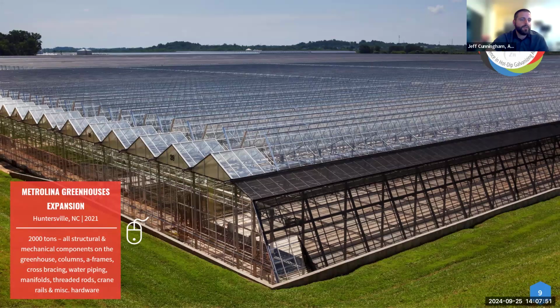So this is the Metrolina greenhouse expansion. This is actually the largest single-story structure in the United States, about 200 plus acres of greenhouses under one roof. The inception was all the way back in 1972, but then they did a huge expansion on it in 2021. They chose hot dip galvanized steel because, one, they're in North Carolina, which is a humid, corrosive environment. So they needed something to withstand the outside weather, but then also inside they use pesticides, fertilizers, chemicals to treat the plants. So they needed something to withstand corrosion from the inside as well. So they chose hot dip galvanizing because it gives that full exterior protection of the steel.